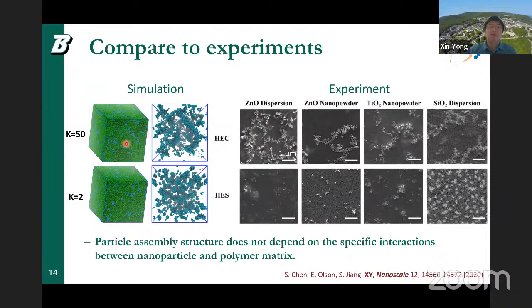You probably can notice here, this system is much bigger than the ones that I demonstrated before, because we want to see whether these elongated aggregates will ultimately connect together to form percolated networks. And so our result shows that in general, it qualitatively agrees well with experiments, where these elongated clusters after evaporation are gonna come close together and then start to form percolated networks. While for the soft polymer matrix, the particles are just isolated, more isotropic clusters.